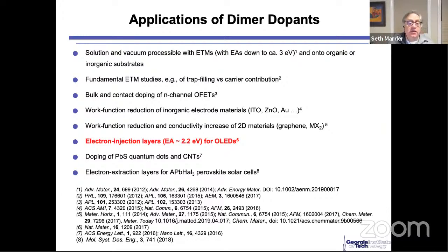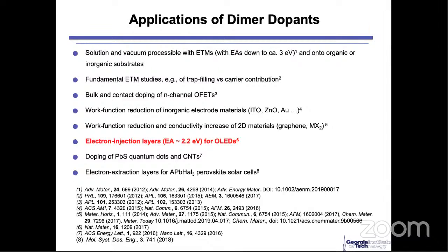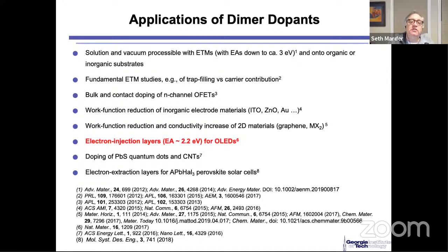So I'm going to talk a bit about these dimeric dopants and some of the hydride dopants and their applications. We're going to talk about solution processable and vacuum processable things just for doping, some fundamental studies of trap filling, a bit of contact doping, modification of work function of standard inorganic electrode materials, modification of work function of 2D materials like graphene and metal dichalcogenides, a bit about electron injection into OLEDs, and actually doing things that are thermodynamically uphill. I'll explain that. And then maybe a little bit on a couple of other things if I have time.